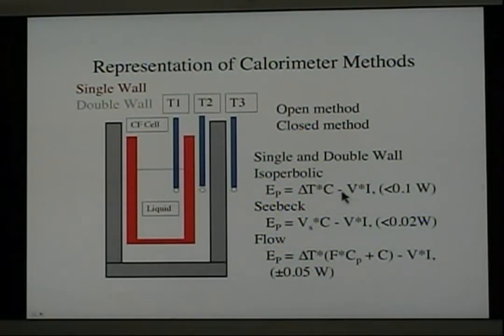In any case, one multiplies the temperature difference across the barrier times the calibration constant, which can be more complex than just a simple number, I might add. From this is subtracted the amount of power going into the cell, which is the product of the voltage times the current. That difference is the excess power.